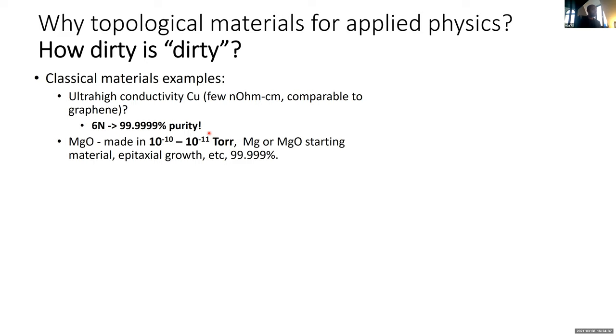But it turns out, basically people were playing around with it and it was always kind of a crap tunnel barrier, too much leaking, not good spin polarization selection. But when you make it in extremely high vacuum, extremely low pressure, it works much better.